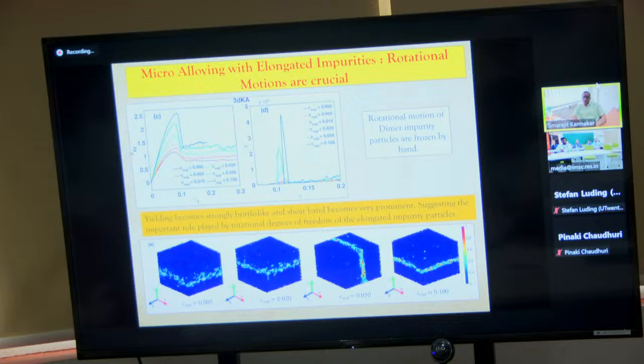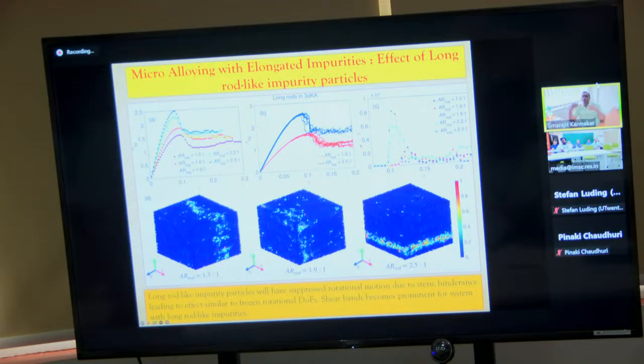So this gave us a crucial hint: if you try to microalloy materials to improve their material properties, particularly the modulus, then these elongated particles can be a good choice, because the modulus increased by a very significant amount. But it also promotes shear bands because of their rotational hindrance. In these simulations, the rotation was frozen by hand, but in reality, if you need shear bands to be present in your system, you can achieve that by introducing long rods. If you increase your impurity rod length systematically, then we found that you can indeed achieve the same scenario as when you freeze the rotational degrees of freedom of the rod particles. A long rod will have very large hindrance for rotation, and they lead to very clean shear band formations.